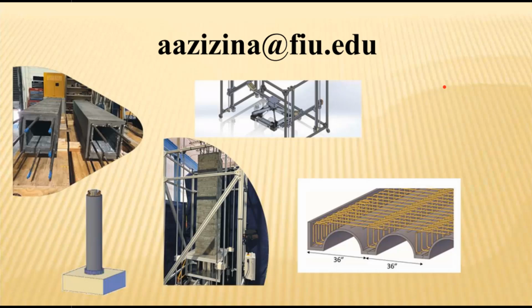With layer by layer, there are different ways, but basically you pump the concrete to the nozzle, and the fiber can have the same issues that we have with concrete when pumping. But in our case, we don't have any issue because between the two rings we have enough cavity that you can pour without any problems.